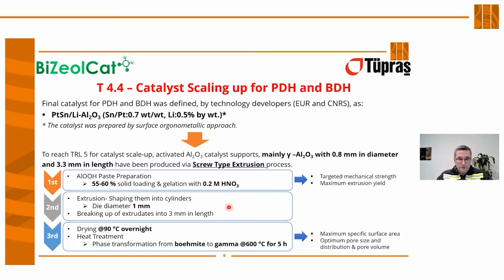Heat treatment was applied to produce gamma phase at nearly 600 centigrade degrees for 5 hours, to maximize specific surface area and optimize pore size distribution and pore volume.